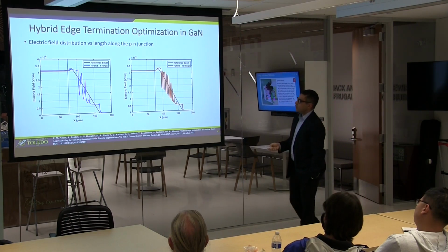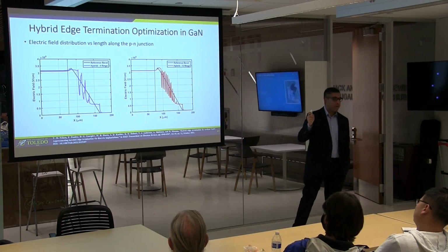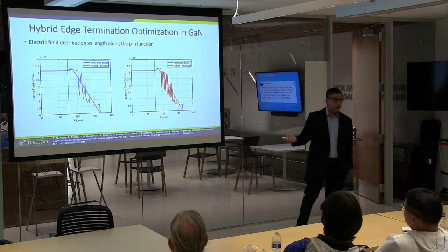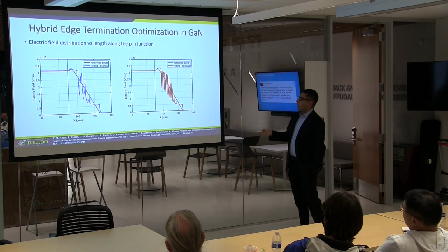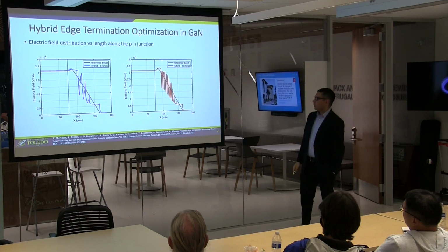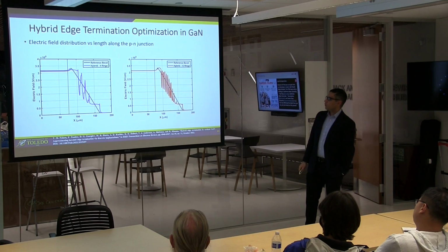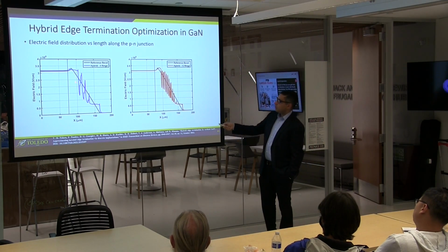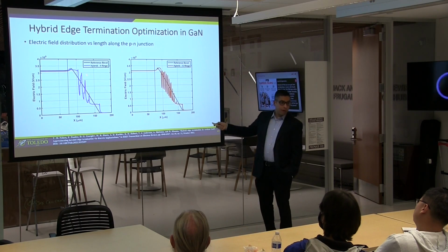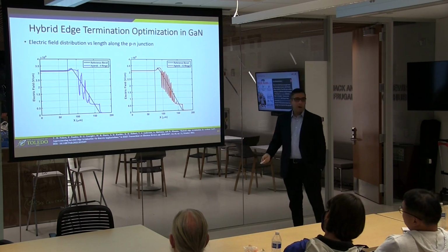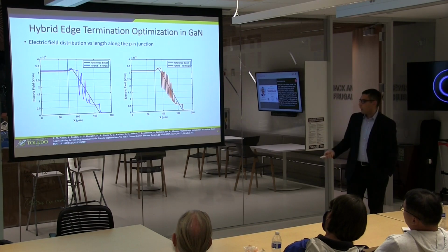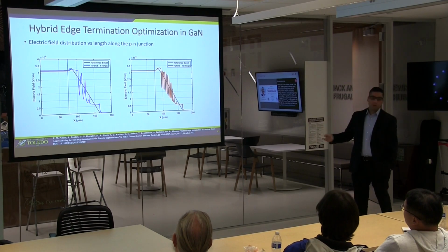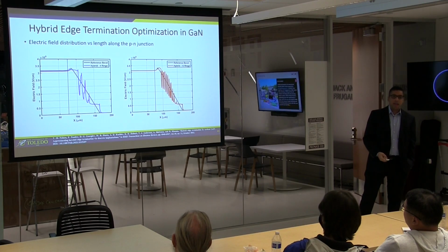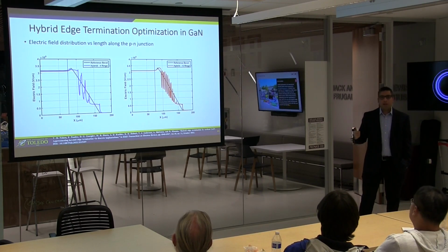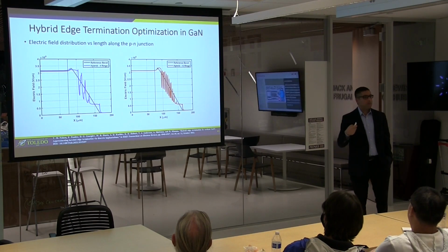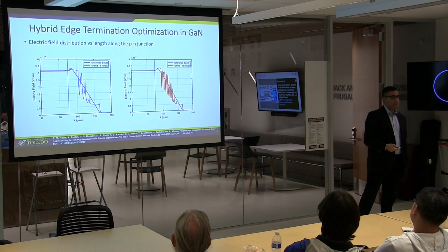On the left-hand side is a comparison of the 4-ring structure with the reference bevel. Again, this is the electric field along one cut line. And then on the right-hand side is a comparison of the 12-ring structure with the reference bevel. So what you can see is our E field at times is above the reference bevel, at times it's below the reference bevel. On average, it's about reproducing it, right? Again, here, our E field above at times, below at times, but on average, it's reproducing it. And again, why is this important? The hybrid edge termination structure is more amenable to fabrication. It's easier to fabricate than the reference bevel.